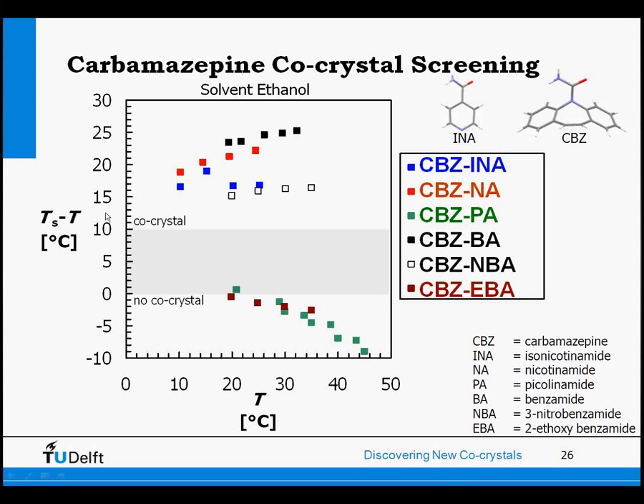And well, we just arbitrarily chose 10 degrees as a point where we think if we have a temperature difference larger than 10 degrees, we have good indications that co-crystals exist. And that is true not only for carbamazepine with isonicotinamide, but also with nicotinamide, that's the red points, with nitrobenzamide, that's the squares, and benzamide, that's the black squares.